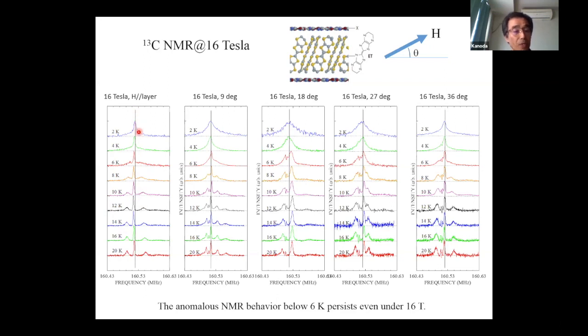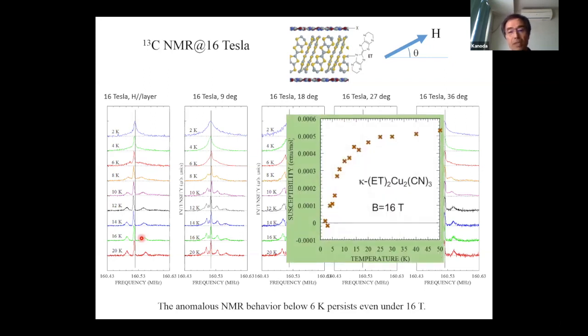This means the same situation as I explained before. Below 6 Kelvin, the local field steeply decreases, and then inhomogeneity occurs. This depends on no angle. For example, for this angle, we could analyze the line profile to yield the temperature dependence of the spin susceptibility, like this, at 16 Tesla: temperature and the spin susceptibility, which is deduced from the spectral analysis. You see the spin susceptibility sharply decreases at low temperatures, maybe around 6 Kelvin. In this case, the spin susceptibility seemingly vanishes.